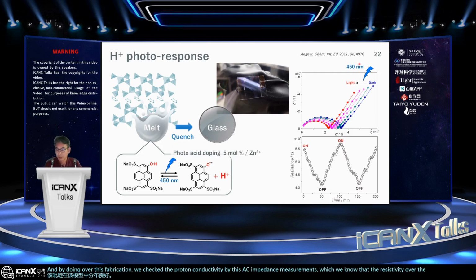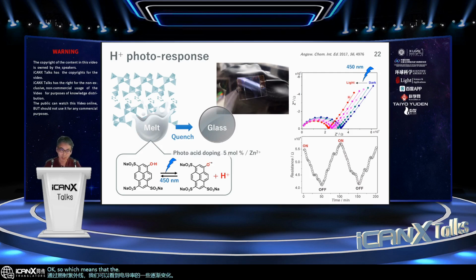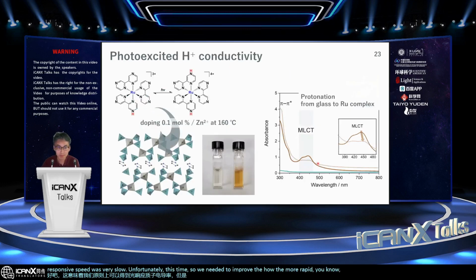And by irradiating that UV light, we can see some gradual change of the conductivity, which is good. So, in principle, we can get that photoresponsive proton conductivity, but the responsive speed was very slow, unfortunately, this time. So we need to improve the more rapid proton conductive switching.